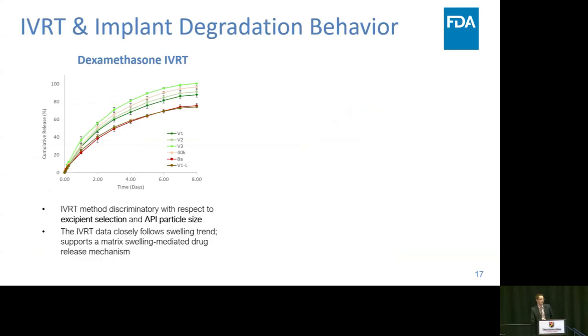And then finally, we did an IVRT method. And I know we've talked a lot about the controversies of different IVRT methodologies and how to come up with an IVRT method that is best suited for the technique and discriminatory with respect to the key variables. Well, we used a static non-sink condition IVRT that we found was discriminatory with respect to the excipient selection as well as the API particle size, which is surprising. And in general, it followed the swelling trend quite well. So it supports that it's a matrix swelling mediated drug release mechanism.